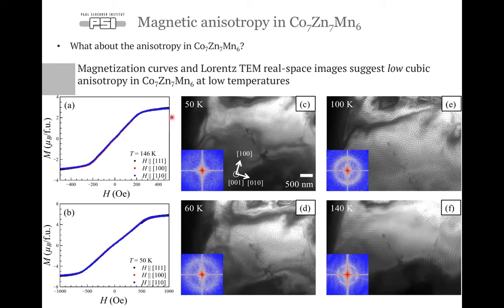Also, with the real space imaging performed with Lorentz microscopy, we can see that for the low temperature phase around 50 K, we have a very disordered magnetic structure that develops into a more ordered but still worm-like magnetic domain structure at higher temperatures as we warm. And finally, we end up with a well-ordered helimagnetic state with a spiral propagation vector along the cubic axis. And we actually can see all three helical domains in one frame in this image at 140 K.